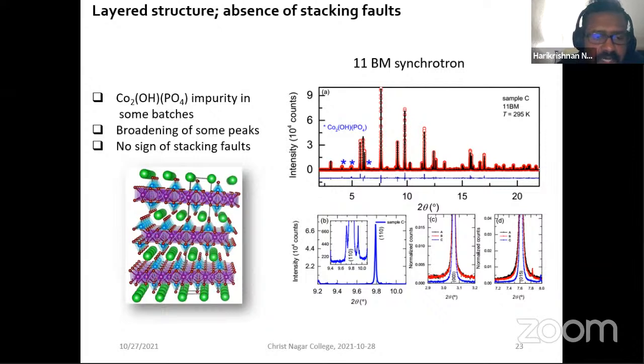And they are separated by other atoms. So you have a three-dimensional structure made by two-dimensional layers of cobalt honeycombs. If you look further using high-resolution X-rays, you see at the bottom that the base of the X-ray diffraction peaks are getting broader and broader. The reason for that is structural disorder, and one main reason is they are layered structures, so they tend to distort very easily. So that's a reason for that broadening.